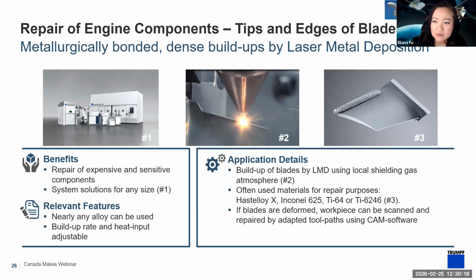This is just adding more material to some place where it's susceptible to wear or friction or even damage from birds and things like stones and pebbles or debris in the air. So if blades are deformed, the workpiece can be scanned and then repaired using adapted tool paths with software. So we're injecting a bit of intelligence into automating this kind of repair process by LMD.